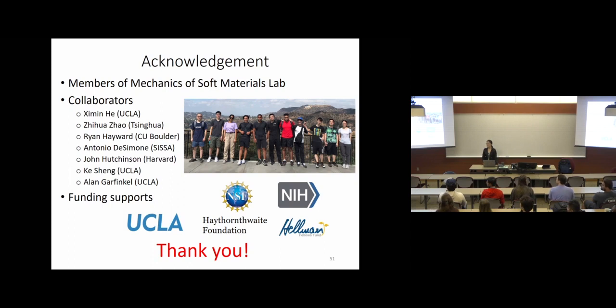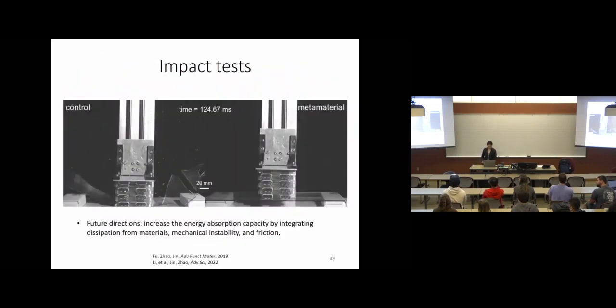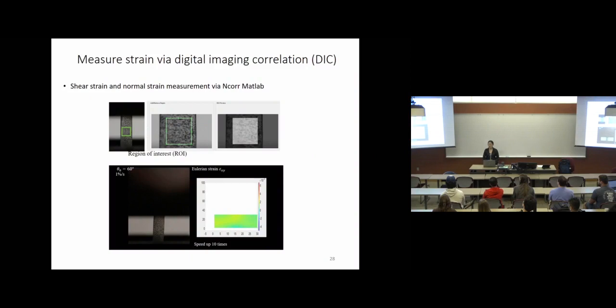So, question? I had a question on the liquid elastomers. In our lab, we had some trouble doing DIC on large deformation polymers because the speckle coating paint cracks earlier than the polymer it's coating. But on, I think it was your slide 29, you showed a video where there was a large deformation. I think it was in tension. And I was wondering if you did anything specific or special to make sure that the speckles stayed on the material without cracking. Yeah, we actually didn't have too much issue of the cracking.